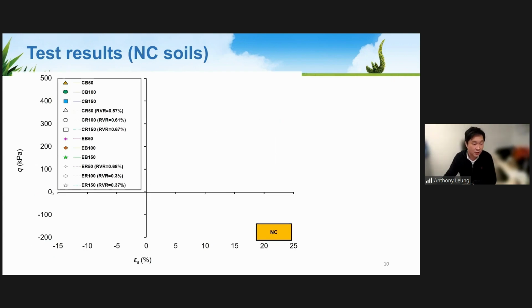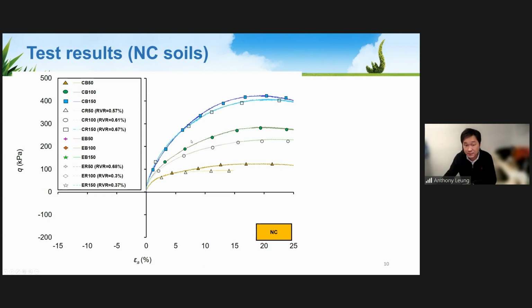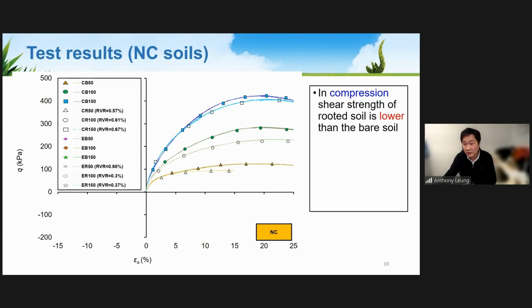So here is the stress-strain curve, deviatoric stress versus deviatoric strain of bare soil and rooted soil, both in normally consolidated condition. Okay, so what you are seeing here are a set of stress-strain curves for bare soil under compression. If I superimpose the result from the rooted soil also under compression, quite surprisingly, you see the shear strength has been reduced by the roots. And one reason is because, as the roots grow in the soil, we introduce interfaces between soil and roots. And actually, the interface friction between the root and soil is much lower than the soil-soil interaction. So that perhaps explains why the shear strength of the rooted soil reduces along compression.